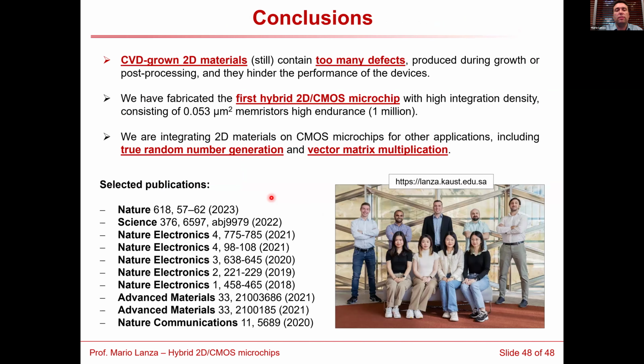So as a conclusion, I will say that CVD grown 2D materials still contain too many defects produced during the growth or during post-processing, and they are hindering the performance of the devices, especially in the transistors. However, you can still fabricate memristors with these 2D materials because you don't need such a high crystal quality, and the memristors tolerate some densities of defects.